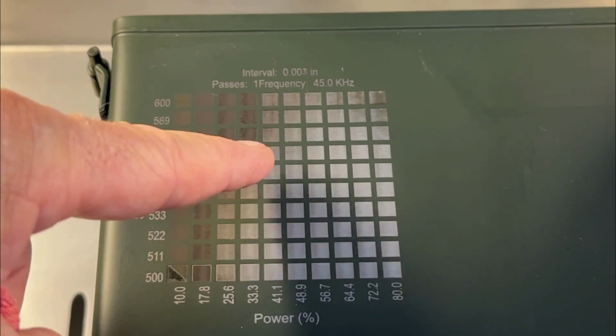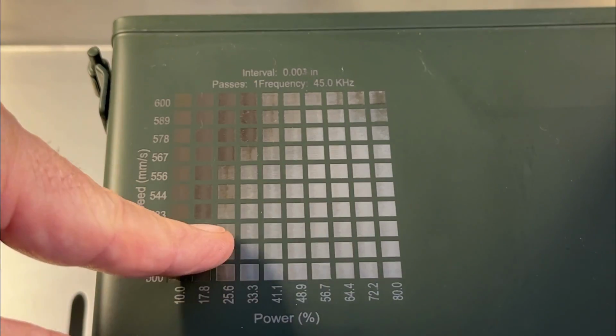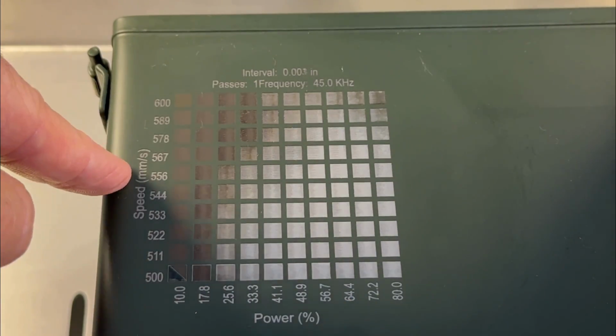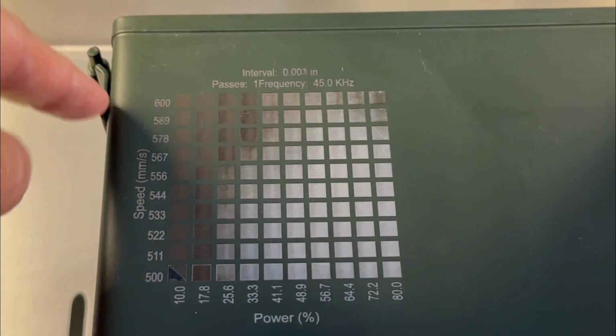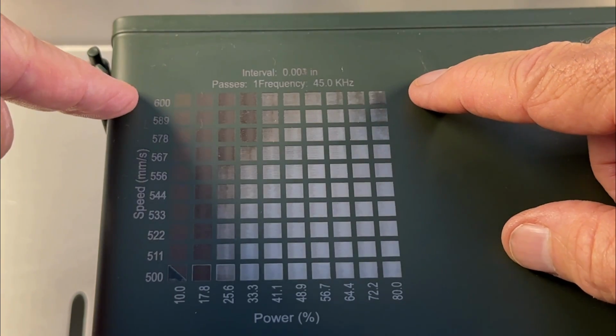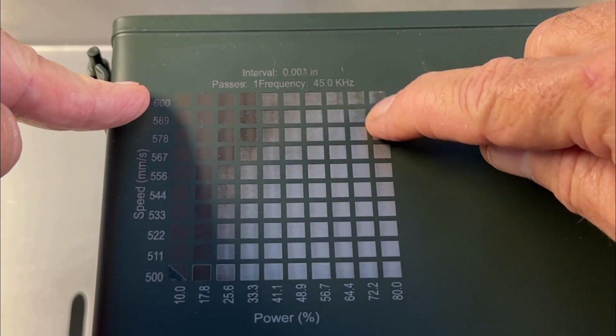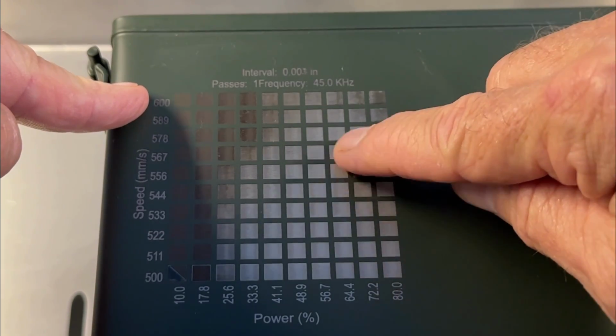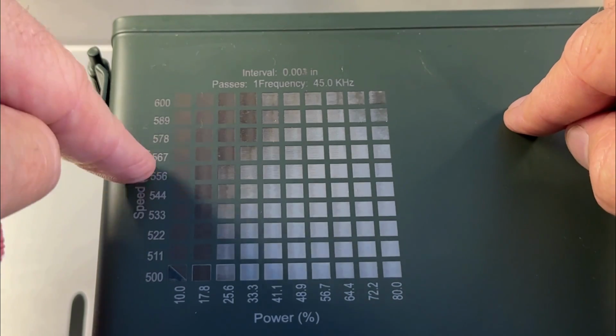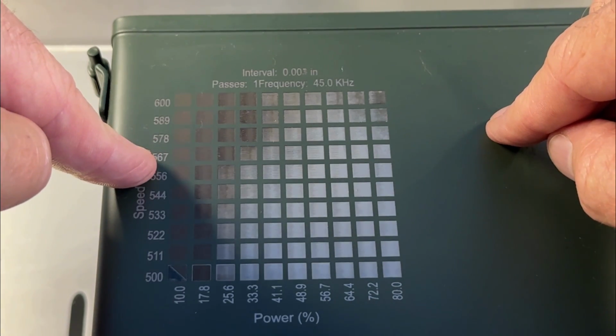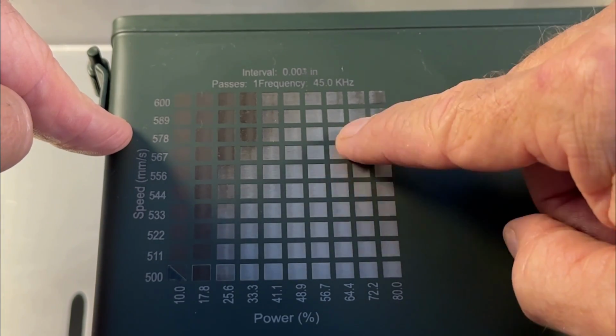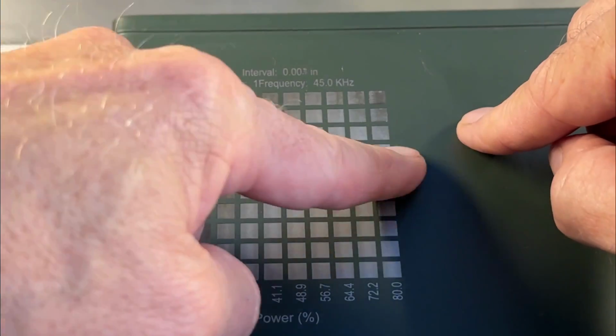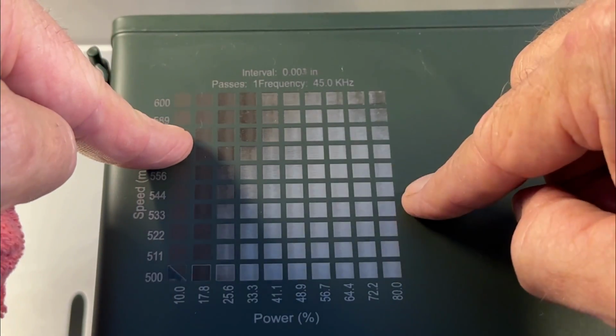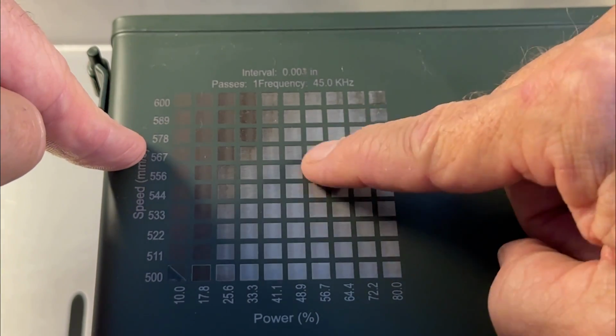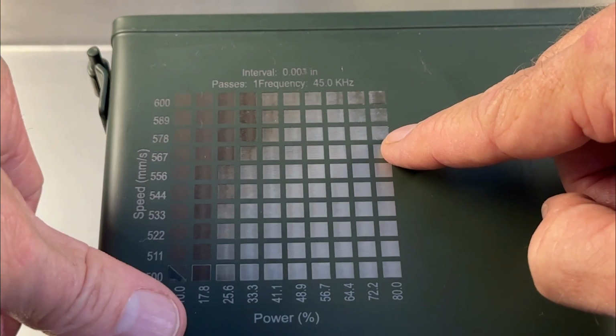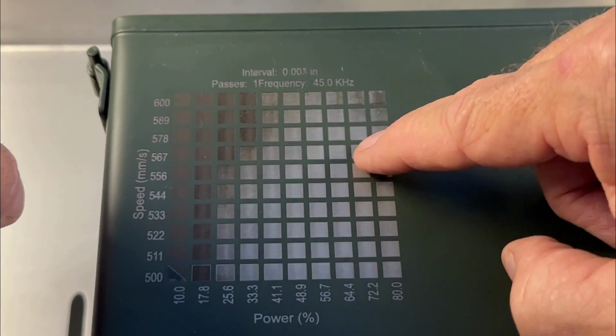And so if you would want to mess with these and try different settings, you certainly can do that. But you can see that what I find interesting is my normal setting for engraving here, 600, which is this right up here, it's not as good as this stuff down here. So these material test cards on things that you haven't done before can tell you quite a bit on what you should be doing. It just looks like to me that down around 550 and around 75% would be maybe a better choice, because I scrubbed on this pretty good and it just didn't come off as clean, where this area right here is a pretty clean engrave. So I don't think I'm going to try to do a two-tone, at least not with these settings. But I know what my settings are going to be for my can.